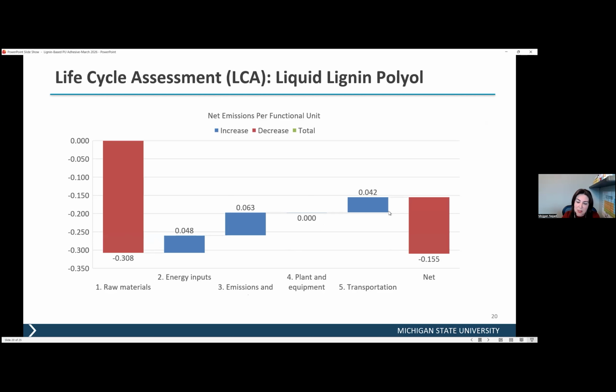Transportation, if they make the adhesive and transport it to the CLT production, is going to use some energy. But if you combine all of it, you can see that we are basically negative. The CO2 emissions, because we are using bio-based materials, are carbon negative. The lignin-based polyol is carbon negative.